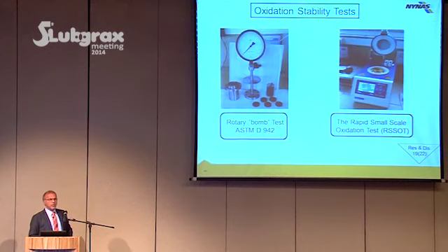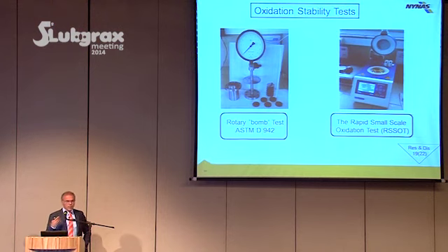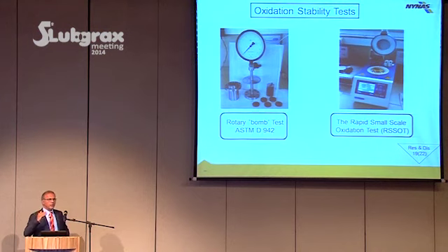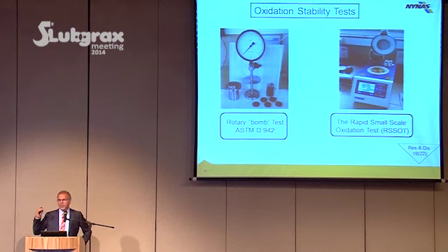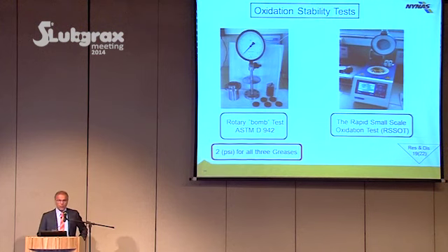This is our last test, but I think it's very interesting, the most interesting to me as a technician. The picture on the left, on my left side and your left side as well, sorry, is a standard test method called the rotary bomb test. What you do is apply your grease for 100 hours at about 100 degrees C, and afterward you measure the pressure drop. If the pressure drop is less than 5 psi, it is okay for fully formulated greases. In this case, we got 2 psi for all three greases, which was excellent.